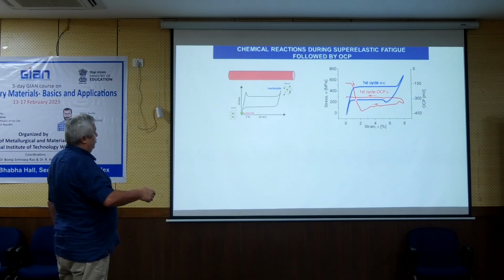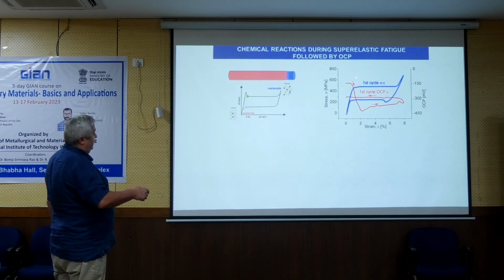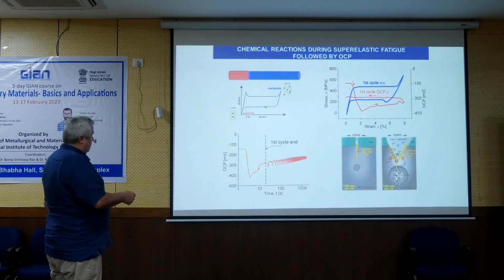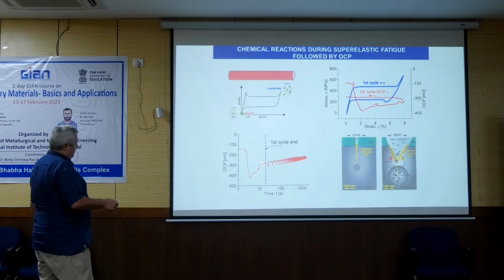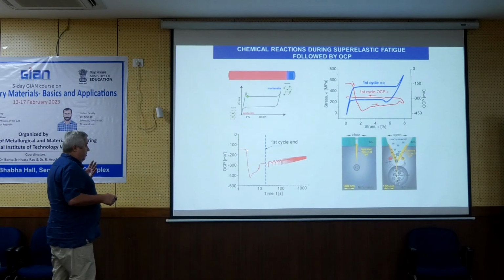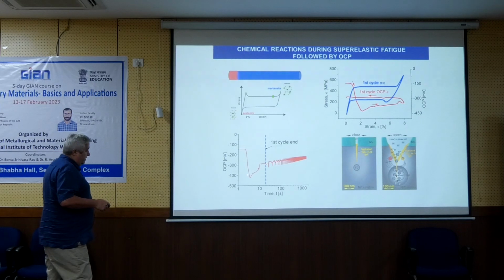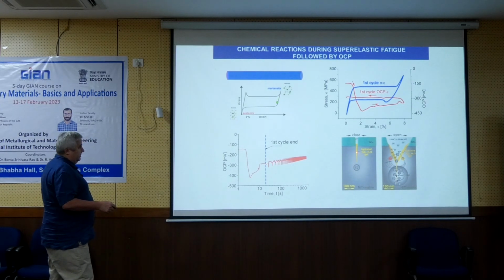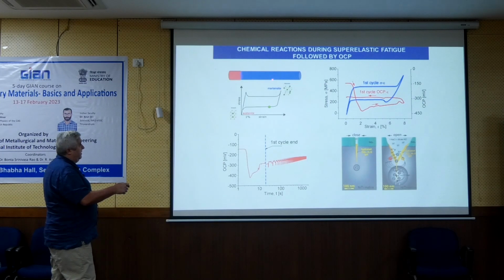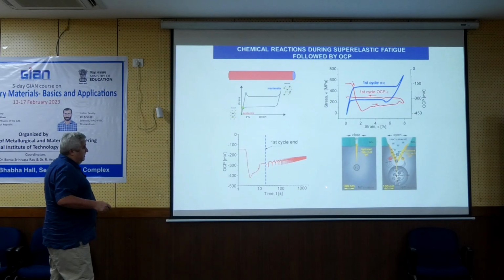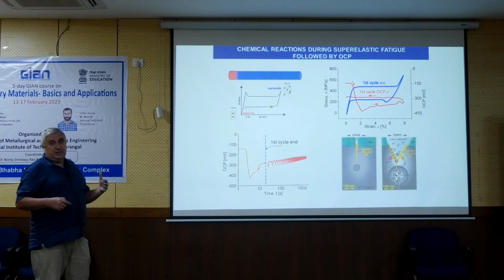So we did the measurement of OCP during the superelastic cycle, and the response is here. So in the beginning you have this decrease, and then the healing during the rest of the cycle, and again decrease, and again. So this is how it looks in time. So basically our concern was confirmed. When for the first time the cracks appear, the OCP goes down, because this is not just one crack, these are millions of cracks everywhere along the surface. But as you are cycling, the passivation proceeds, you can heal it, but the value is still half. This change of almost 150 millivolts is a very big change in open circuit potential.